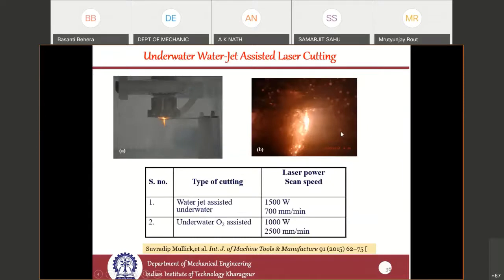And the other application is stent cutting. One can use thin steel or tantalum sheet or tube to finely cut, without any burr or microstructural or heat affected zone in the tube. Then at IIT Kharagpur we developed underwater water-assisted cutting, and we could also create very good quality of cutting by this method using our high power fiber laser.